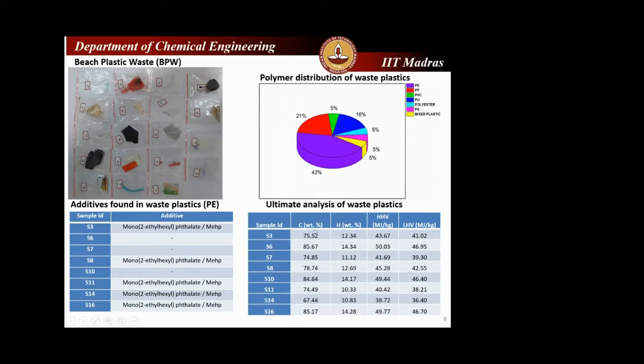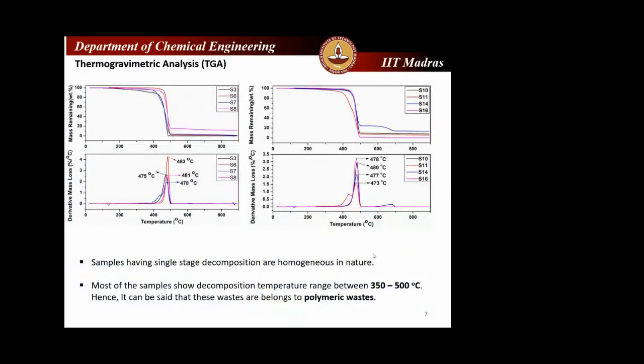I subjected these polyethylene samples to ultimate analysis and got the carbon weight percent, hydrogen weight percent, and calorific value. These are made from fossil fuel and natural gas, so obviously their carbon and hydrogen content is high, with a heating value in the range of 40 to 50. So I narrowed down the matrix of 19 plastics to polyethylene plastics and subjected them to thermogravimetric analysis. These are all polyethylene samples.